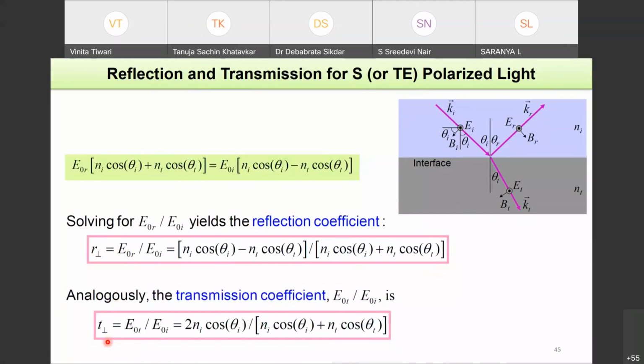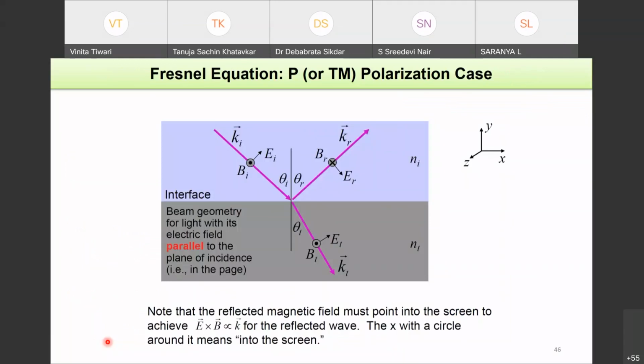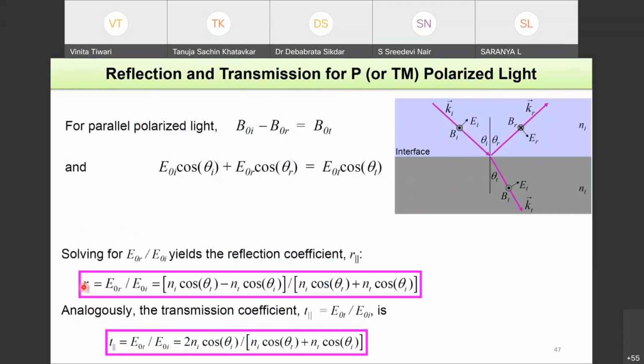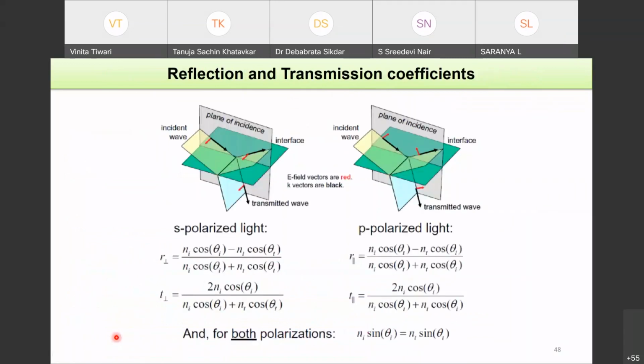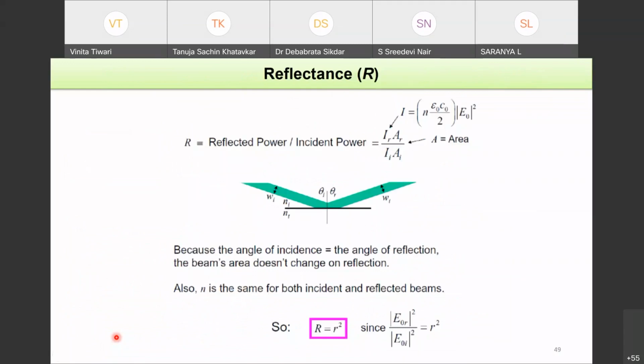And once you obtain both these coefficients, you can also repeat the same exercise for P polarized light or TM polarized light, and you will obtain the equations of R parallel and T parallel. So these are basically reflection and transmission coefficients. So this is the summary of both reflection and transmission coefficients. Now from that, what are we able to obtain? We are able to obtain the reflectance. That is reflected power over incident power. Now reflected power is IR AR over II AI. Okay. So here you see the beam width is remaining the same, so the area will remain the same, and you can obtain reflectance as the square of the reflection coefficient.